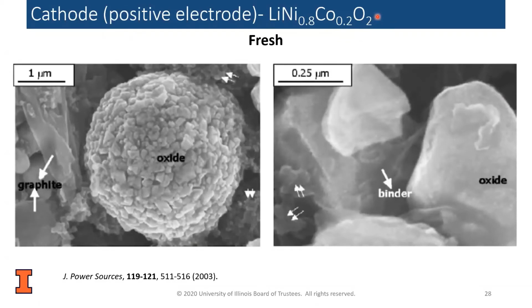But because the material is just made for reagent grade material, it won't make a very good battery, that is. And so here, if we look at higher magnification, we can actually see the other constituents of the oxide. The electrode, we see the binder right here, and some carbon black right there.